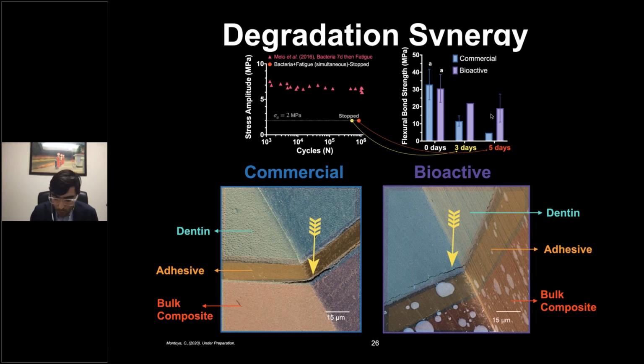We're beginning to conduct fluorescence visual imaging. If we think about the block, we have the dentin side, the adhesive, and the bulk composite. We're seeing that failure is happening in different locations. For commercial, we see failure happening in the bulk composite and adhesive interface. For the bioactive, we see failure happening in the dentin side rather than the composite side, and so on and so forth.